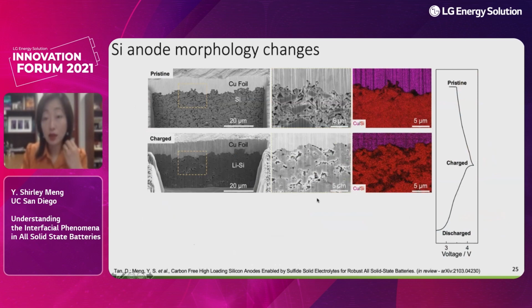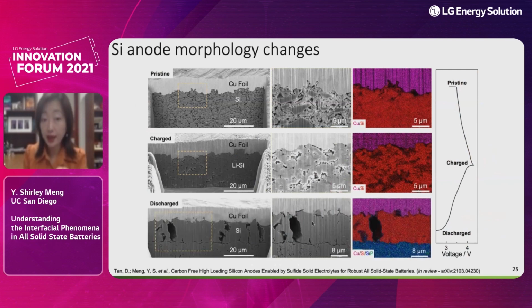What's most striking for us is when you start to delithiate, we form this type of very columnar, large grains of delithiated silicon, and the morphology after the first charge compared to the pristine state is completely different.